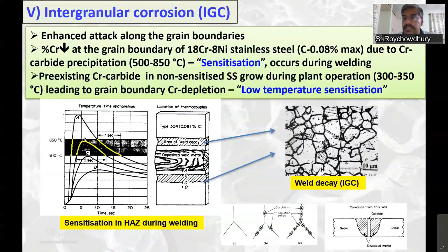So as the name suggests, here the corrosion occurs preferentially at the grain boundaries. The grain boundary always has a higher tendency to corrode, but under certain conditions, the tendency to corrode increases manifold. So for example, sensitization in austenitic stainless steel, 18-8 stainless steel, which contains around 0.08% carbon.